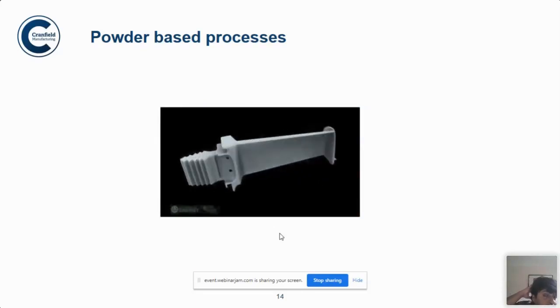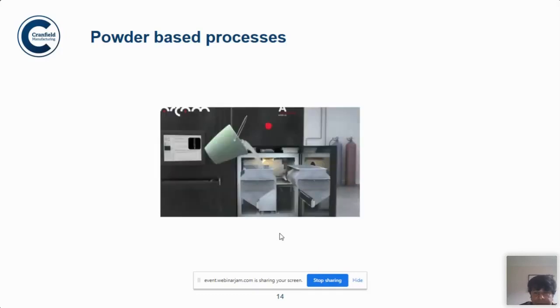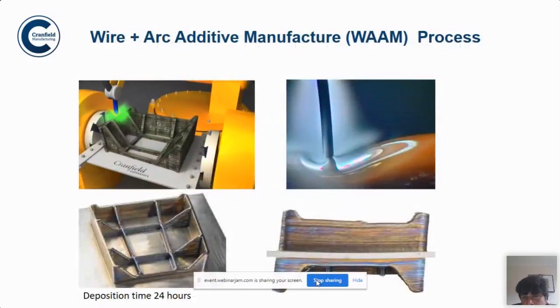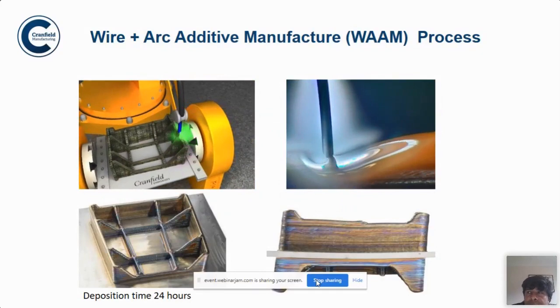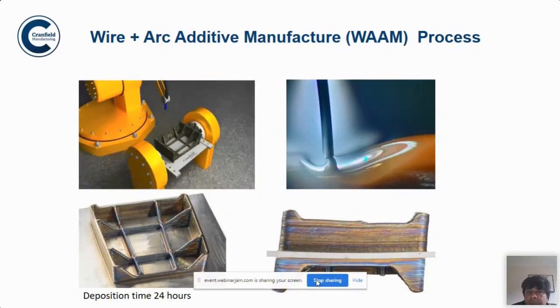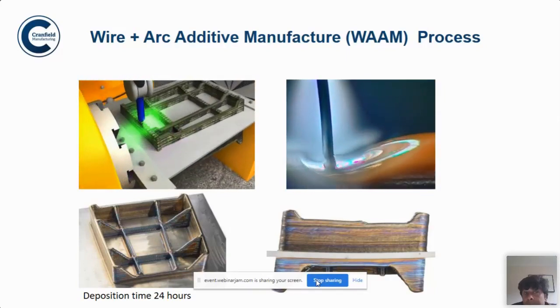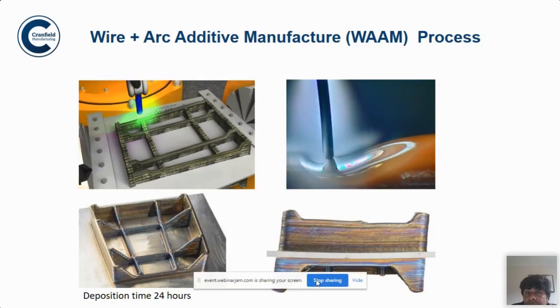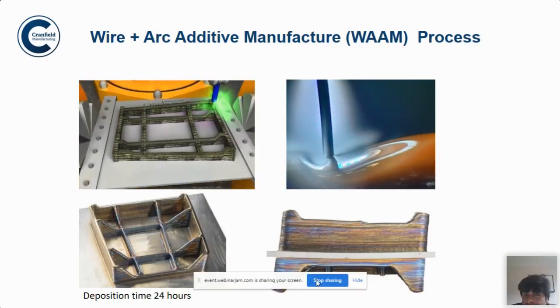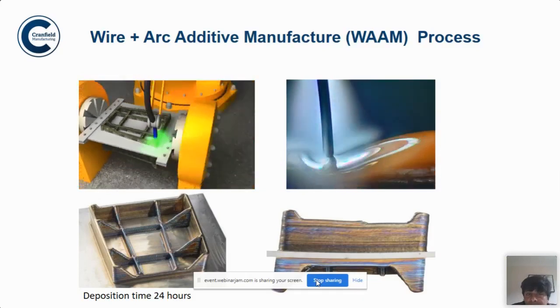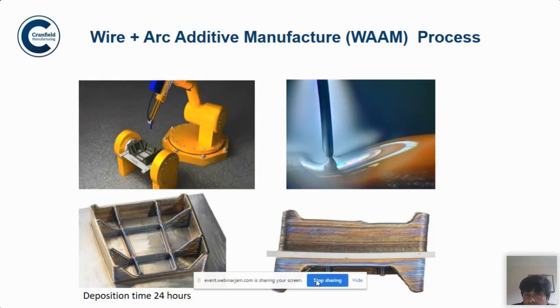So this process is an extremely important process, and wire plus arc additive manufacture is a different process. I'll just go to the next slide. Yeah, so this is wire plus arc additive manufacture. In the previous process, you have seen powder and laser. They are very good to create very complicated geometries, but the deposition rate in that process is very low. That previous one is near net shape, so it is very close to the actual shape and the dimension of the component.